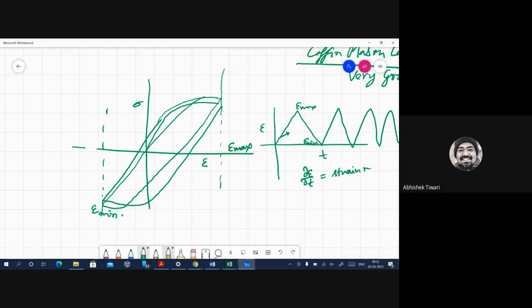So the whole behavior also changes if you change this thing, because strain rate simply means that this much amount of deformation is given in such and such amount of time. If you don't give much time, diffusion will not happen. If you give much time, diffusion will happen. We conducted this test at 550 degrees Celsius, so diffusion should not be an issue, but of course, there can be an inertial effect if you increase this to a very high value.